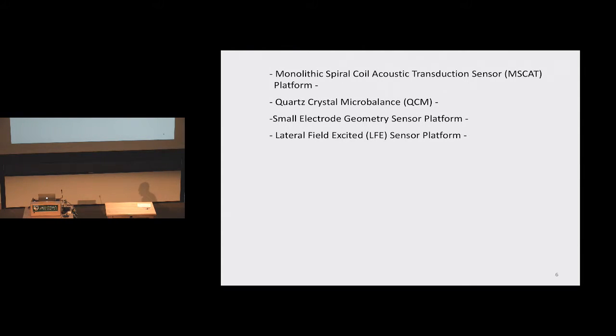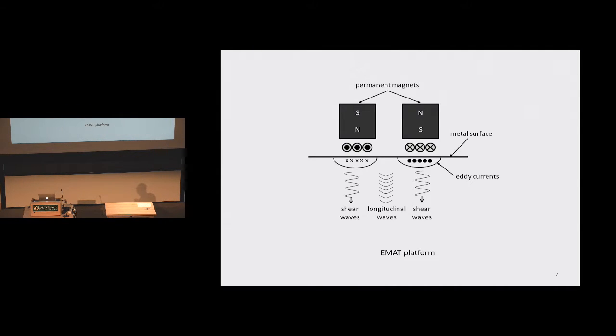So when we speak about acoustic wave platforms, we're not talking basically one or two or three. There's been a whole combination of them that have been published in the literature. The so-called EMAT platform, basically it consists of two magnets on the top. Those magnets have a coil underneath them. The magnets are here, the coil here. That sets up eddy currents in a conducting material down here, which via the Lorentz force, remember I dL cross B, generates a force which can be manifested as longitudinal or shear waves.